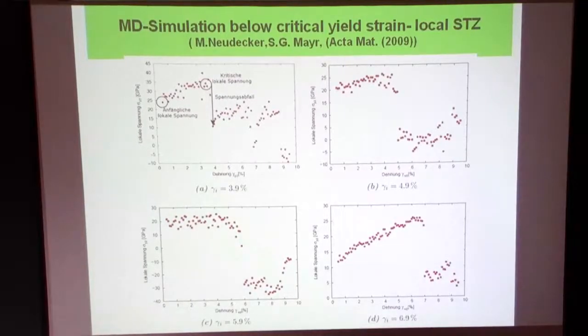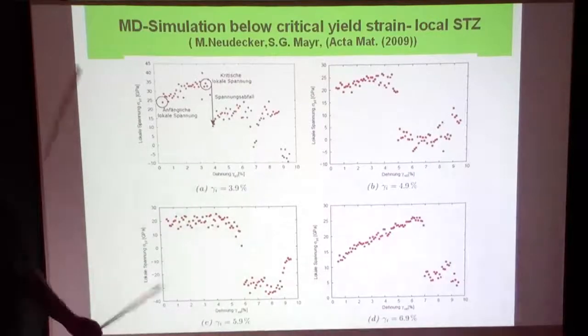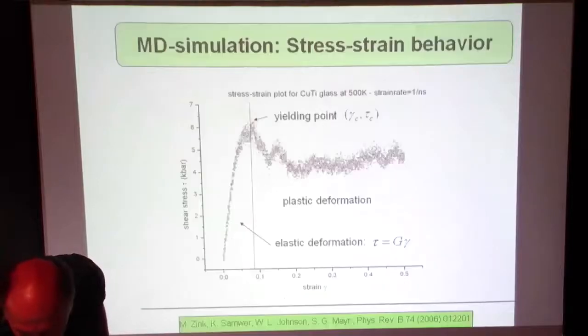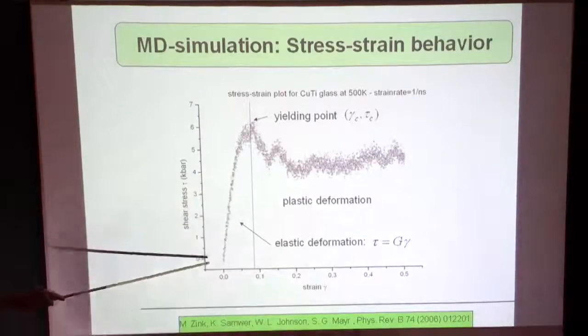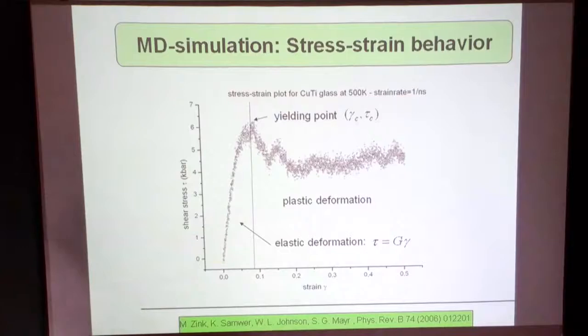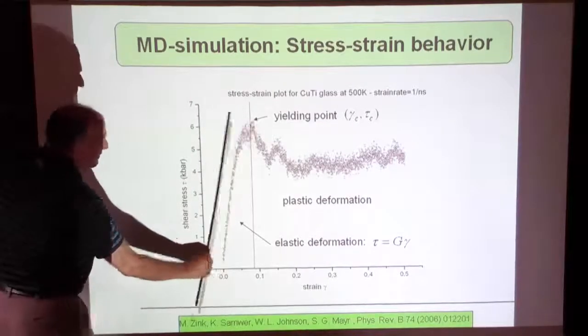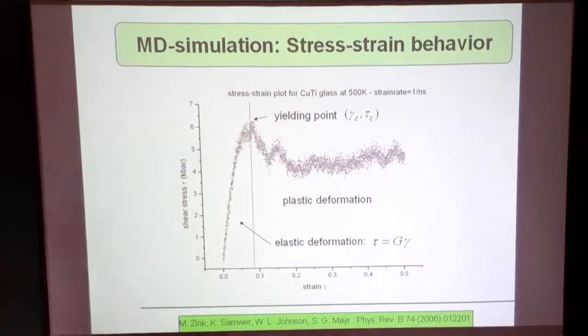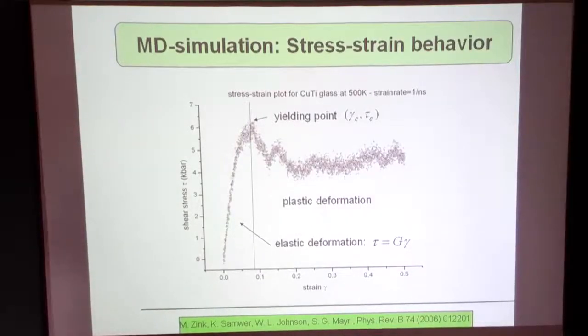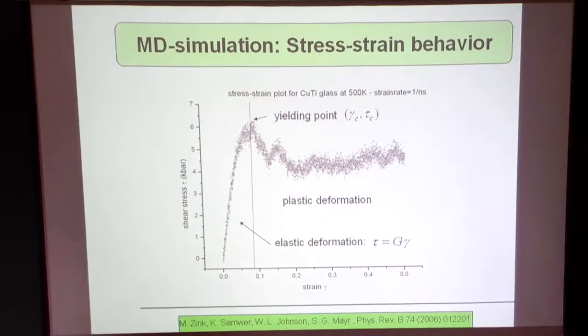Is this in the beginning loading state? Yes, it is below critical yield strain. Okay. So there is almost no real elastic region in the metallic glass. They are all starting to flow. It just depends on the time. When you measure very slowly, you find a linear curve, more or less, like most people did. If you do it fast enough, you will see that there's activation going on, and this activation has a time scale, the beta process I showed you, or the temperature scale.